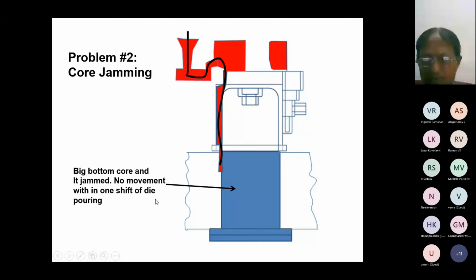And during production, when the metal comes at a very high speed on this one, see, this is the metal entry, then about 4 hours it gets jammed. Then we used to remove the core and remove this material and apply Molykote coat also and then assemble. This will work for only 4 hours. Afterwards, again the metal will go inside and we have to remove it again.